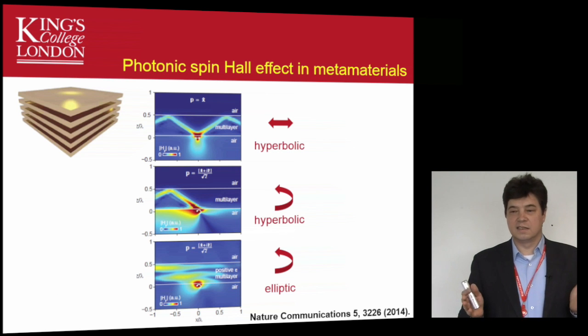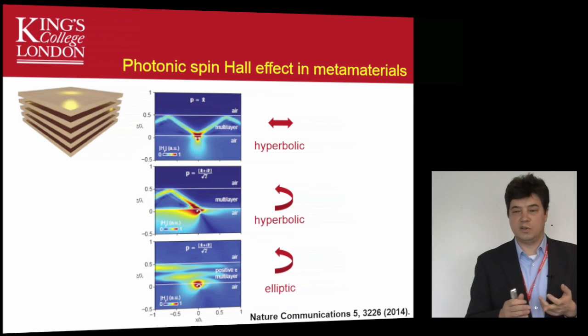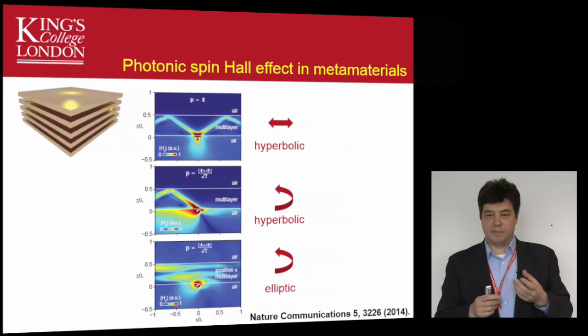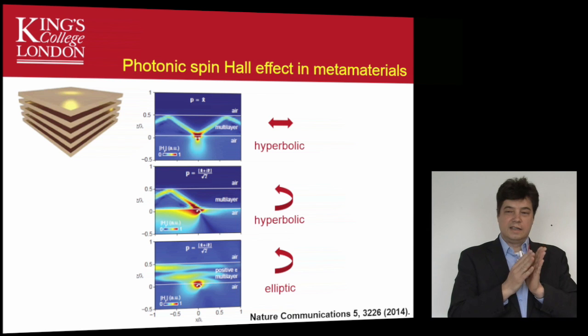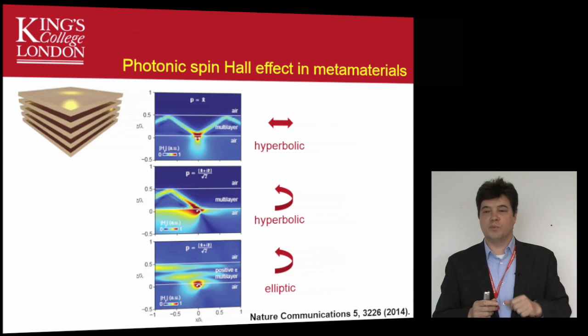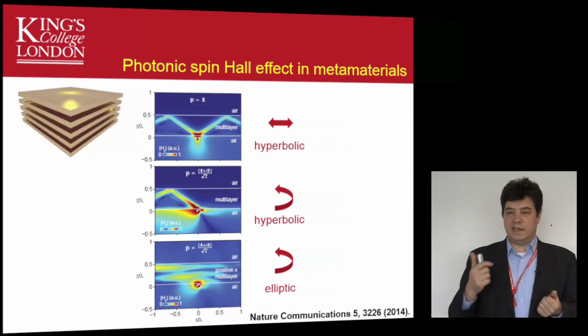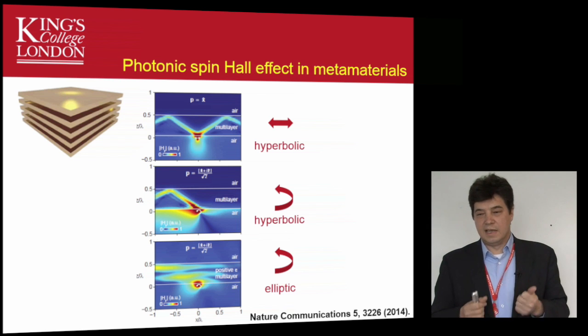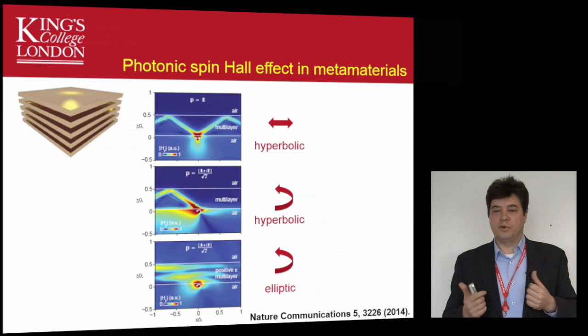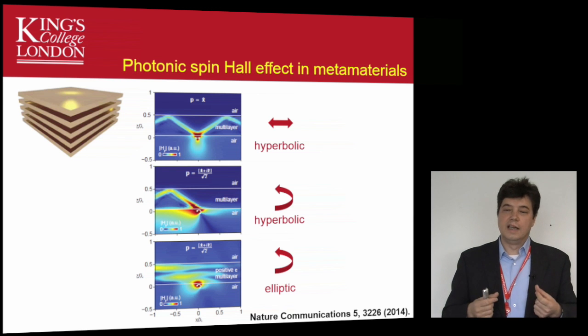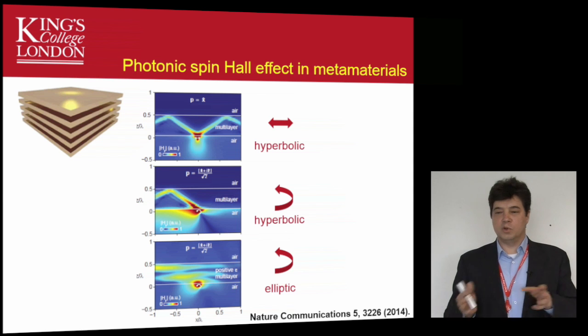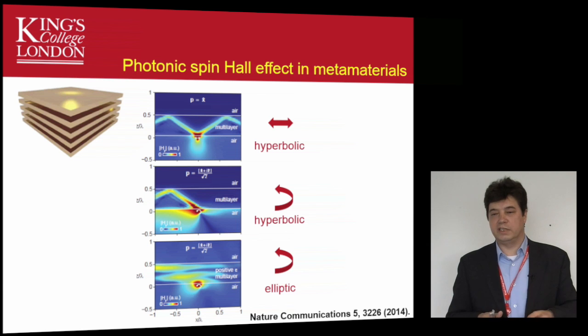This effect is universal for fibers, surface plasmon polaritons, and metamaterials. In an example of metamaterials composed of gold-dielectric multilayers behaving as hyperbolic metamaterials, these can support very strongly confined waveguide modes. If these waveguide modes are excited with a linearly polarized dipole they excite in both directions, but with a circularly polarized dipole we can control the directionality. For hyperbolic metamaterials, which is an anisotropic material, there can also be elliptical dispersion where metamaterials support waveguide modes that are not as strongly confined - but this polarization control works for both hyperbolic and elliptical modes, with different confinement but controllable directionality.